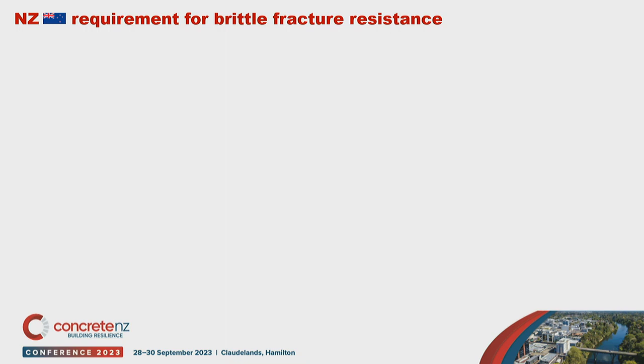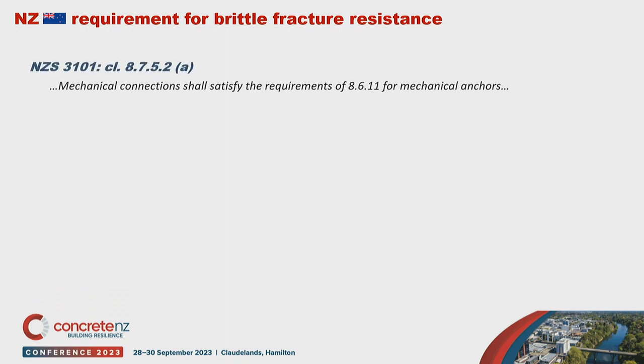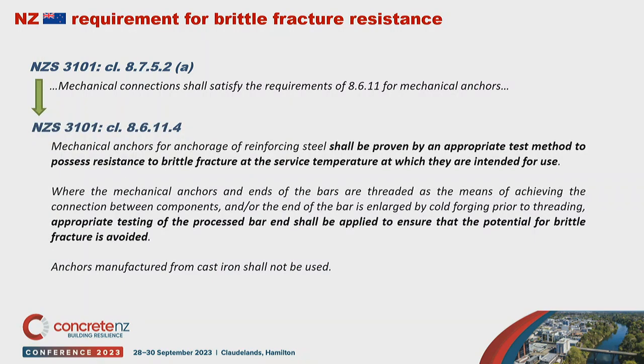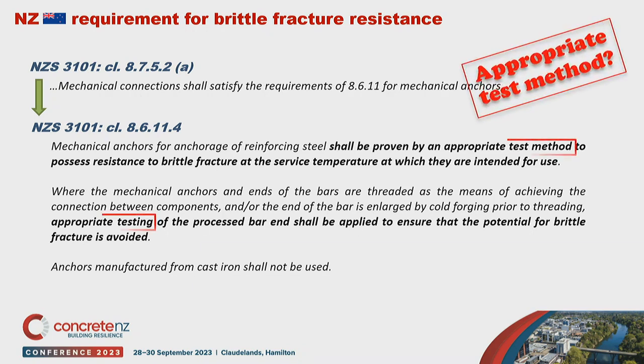And the requirements for brittle fracture resistance in New Zealand come from 3101. From 3101, we know that mechanical connections need to satisfy the requirements for mechanical anchors, which in turn are required to be proven, through an appropriate test method, to possess resistance to brittle fracture. And this is not just for the coupler, but is extended also to the processed bar ends. And also there is a requirement for anchors and couplers not to be manufactured from cast iron.